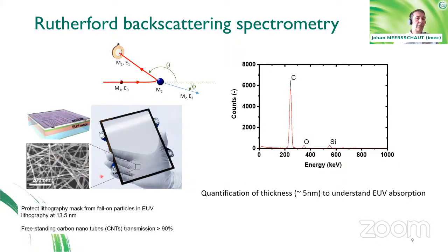The attractiveness of such a pellicle or membrane is that on the one hand, it can protect material particles from going through, but on the other hand, the thickness of such a pellicle is extremely small. And people are considering using such pellicles as a protection for the EUV mask in EUV lithography. The challenge for the application in this environment is that these materials must have a high transmission for the extreme UV light. So these pellicles have to be made as thin as possible.